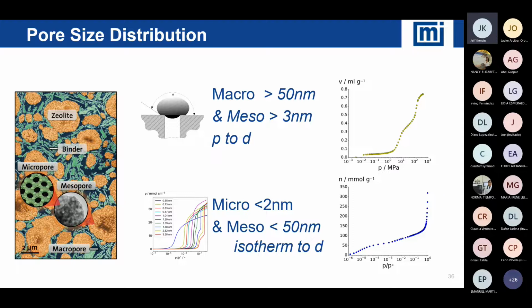Okay, so looking at these hierarchical materials, and the picture on the left side is a good image of a hierarchical material and how complex they are. You've got zeolite crystals, you've got some binder material, so something to help maintain the shape. And then within that, there are macropores, mesopores, and micropores. And from the characterization standpoint, it's challenging because I can use mercury porosimetry for the larger pores, the meso and macropores, and I can use gas adsorption for the micro and mesopores, but how do I put them together?